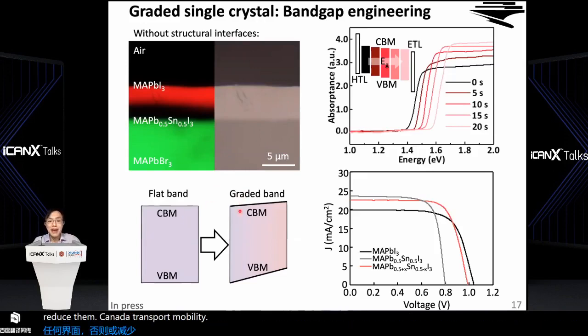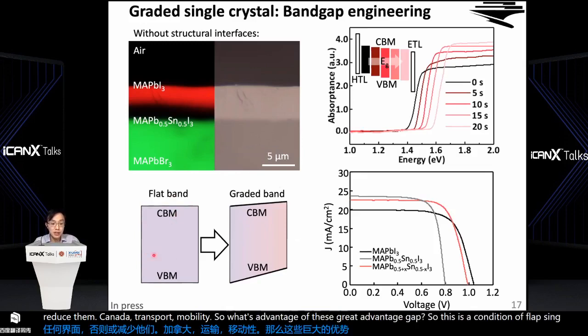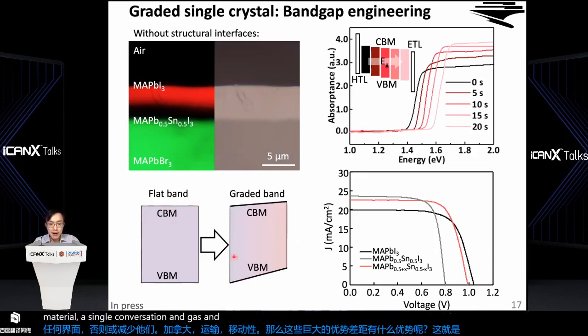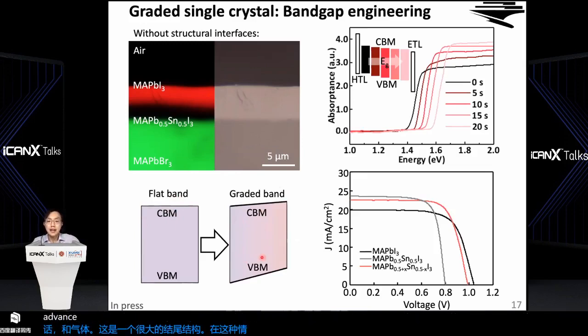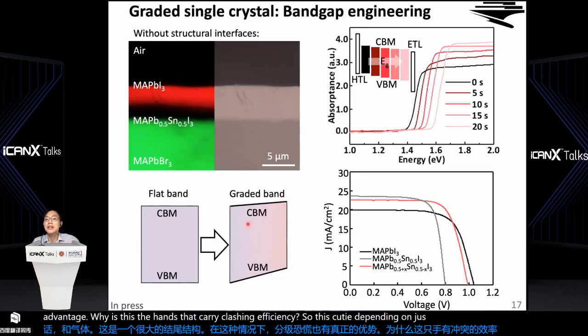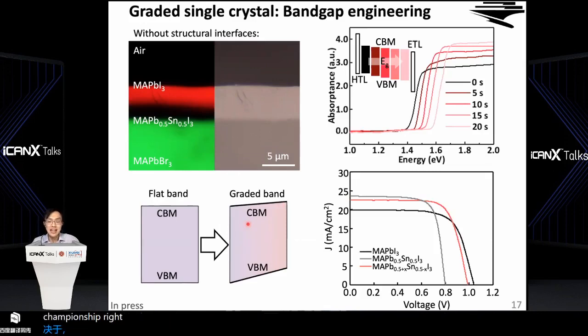So what's the advantage of this graded band gap? So this is a conventional flat single material, single composition band gap. And this is a graded band gap structure in this case. So this graded band gap has two advantages. One is this enhanced carrier collection efficiency. So this tilted band gap just mimics this built-in potential of a PN junction, right? So this built-in potential can enhance this carrier drifting, so that it can reduce the carrier recombination in this built-in potential region. And this tilted band gap edge can do a similar thing, right?